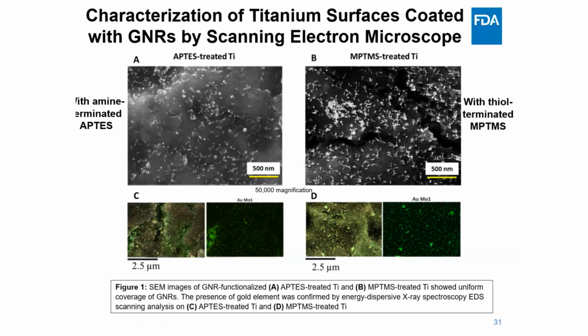MPTMS coated surfaces. However, when you compare these two A and B images, you can see the MPTMS treated titanium surface contains more uniform and dense gold rod coatings compared to the APTES treated titanium. The green signal in the EDS map on the bottom confirms the presence and the distribution of gold, with especially effective coverage on MPTMS treated titanium. So this data confirms gold coatings on titanium surface both visually and chemically.